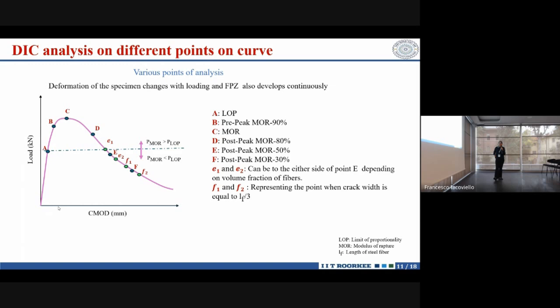First is the LOP point, and then we have a pre-peak MOR at 90%, and this is the MOR point, and this is the 80% of the post-peak MOR, and E is the 50% post-peak MOR, and this is 30%. And this small E1, E2 can be to the left or right, depending on the fiber volume. And F1, F2 is the point representing the crack width equal to lf/3.